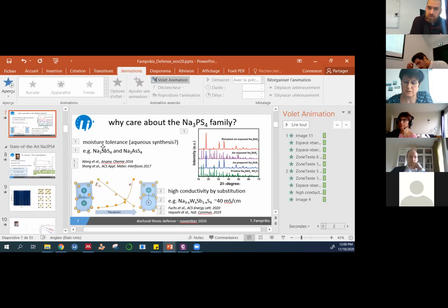We have done this, not in the framework of the work that I showed here, but we did consider it in a work that we're doing with Piero Canepa: the energetics of all the possible defects that you can have in an A3PS4. And indeed, it wouldn't be surprising necessarily for an ion conductor, but the sodium vacancies are actually some of the most energetically favorable defects. So that is consistent with the proposition here, yes. And also the sulfur vacancies as well, I should say, yes.